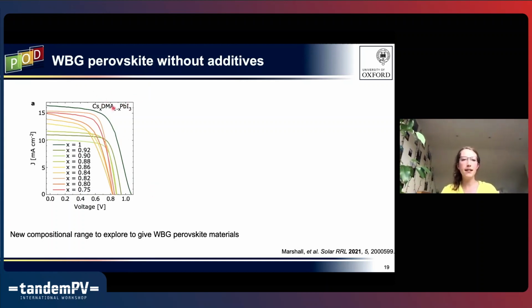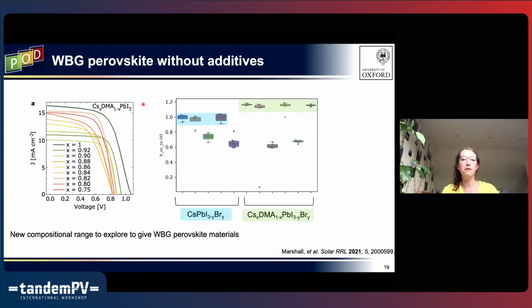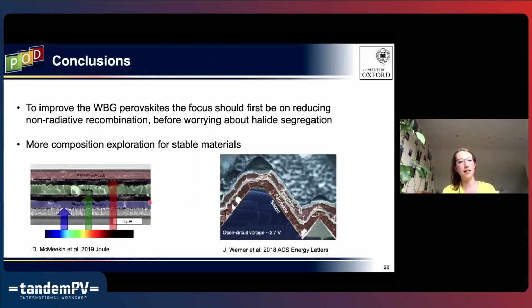But the ability to put dimethyl ammonium into the A site actually opens up a whole new compositional range to explore for these wide bandgap materials. So you can see here we've just done it with the triple iodide, but if we start mixing iodide and bromide, we can get fairly high VOC with some of these new compositions. And this is before doing any sort of additives or treatments. So that's really, really exciting.